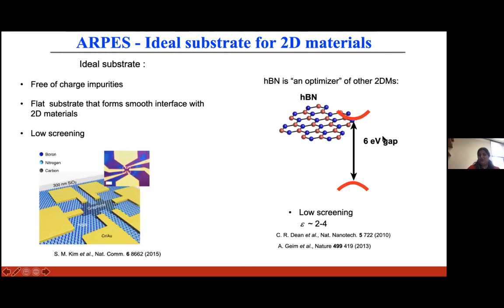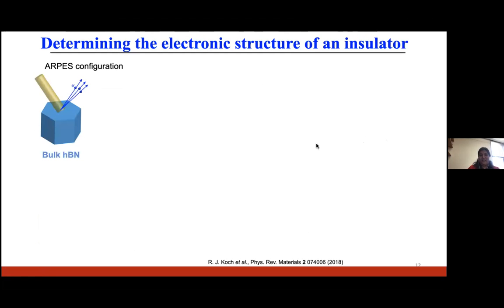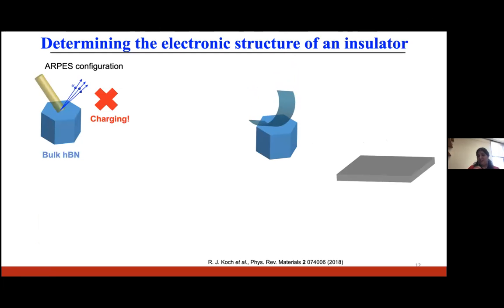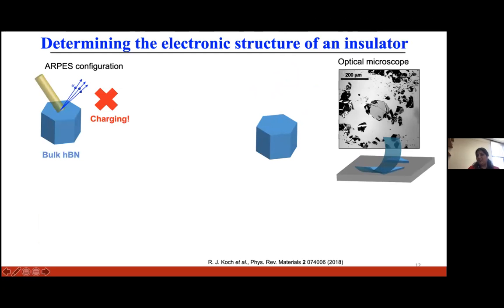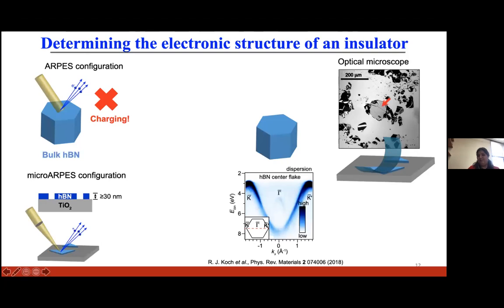So it means that if you try to do ARPES measurements on bulk HBN, then you will get a lot of charging issues. And so in order to circumvent this, what we did was we exfoliate or thin down the HBN and put it down on a conducting substrate. And so here's an optical image of our exfoliated HBN flakes on a titanium oxide substrate. And here the thickness of the flake is about 30 nanometers. And as you can see, we can now get the dispersion of the HBN along the K gamma K direction.